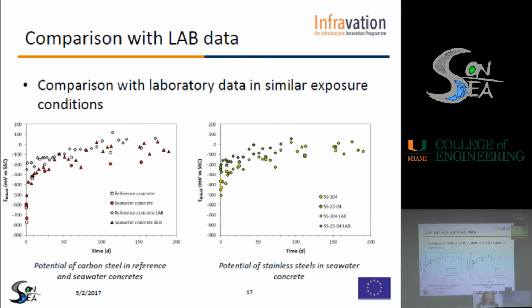But because of the relatively high values of potential, we can assume that both carbon steel in reference concrete and also the two types of stainless steel in seawater concrete are not actively corroding. At least they are not yet actively corroding.